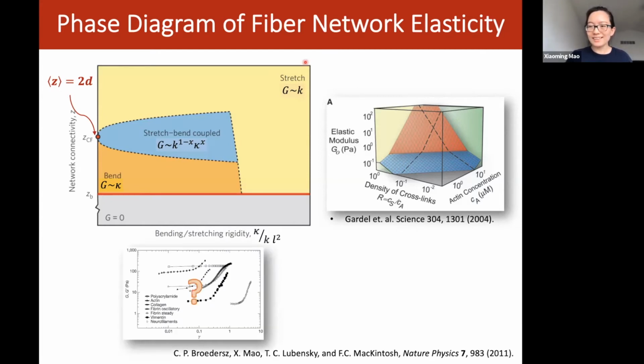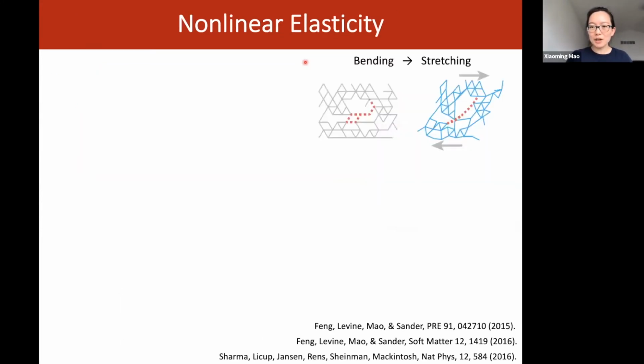So then, what about the nonlinear behavior? The nonlinear behavior has a similar geometric origin. If you think about a network that is below the central force isostatic point, in the linear elasticity regime it is very soft and has a lot of floppy modes. It cannot carry stress using the central force springs. But as you stretch it out to the nonlinear level, you stretch out the zigzag lines in this fiber network and prepare central force chains that can carry stress. So there is a bending to stretching crossover as you go to nonlinear elasticity.